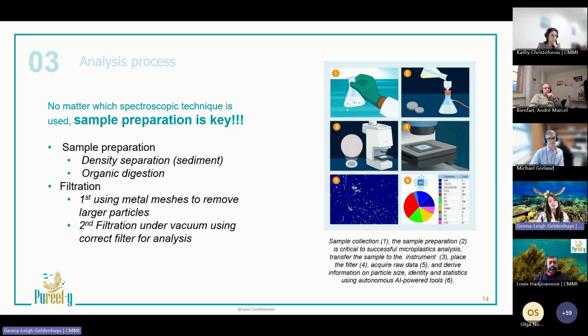So the key message here is that no matter what spectroscopic technique is being used, sample preparation is absolutely critical. For marine samples, this generally involves a series of steps, including density separation and organic digestion to remove biological materials. The sample is also filtered in 2 stages, the first one using metal meshes to remove larger particles, and then the second one is to collect microplastics on appropriate filter material for FTIR analysis. And always, throughout the process, strict measures must be taken to avoid contamination, as Olga very nicely explained.